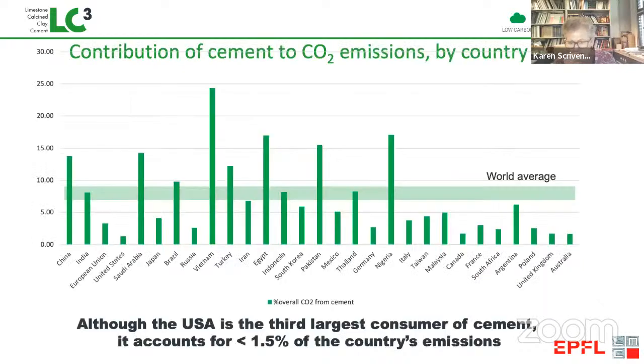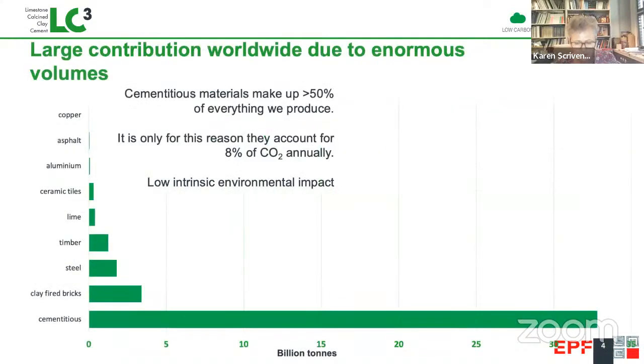So today, if we look at how much CO2 is coming from cement in different countries, we see India is pretty much near the world average of about 8%. But if this increase continues, and if, on the other hand, India is successful in reducing the CO2 intensity of its energy, then this share is likely to increase. Now, we can't do away with using cement in concrete, because concrete is by far and away the most used material, more than all other materials put together.